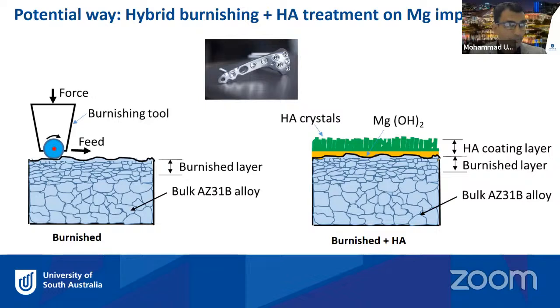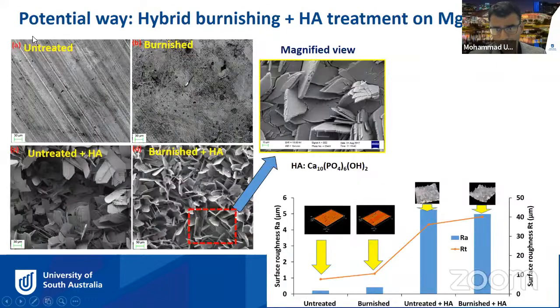But we don't want the material to not be degraded. We want the material to be degraded, but we just want to delay the process by creating this sort of layer onto the magnesium alloys. So we have done some of the study here. We looked into the untreated surface and the burnished surface, and then we applied the coating on top of the surface, and this is the HA coating.